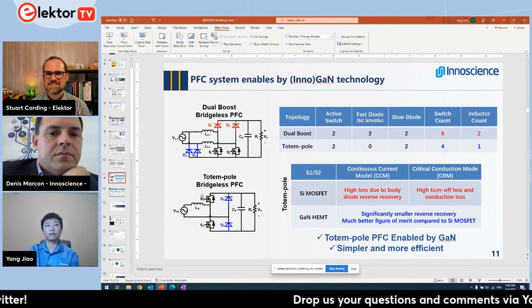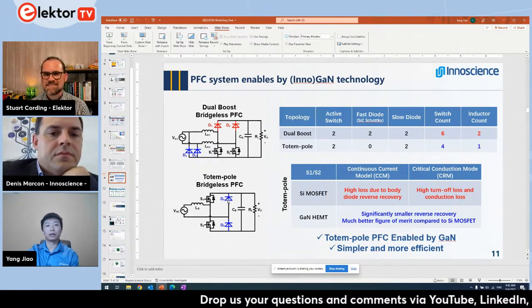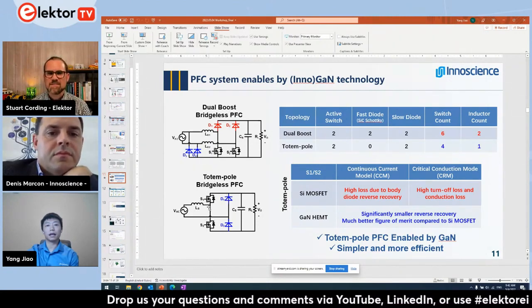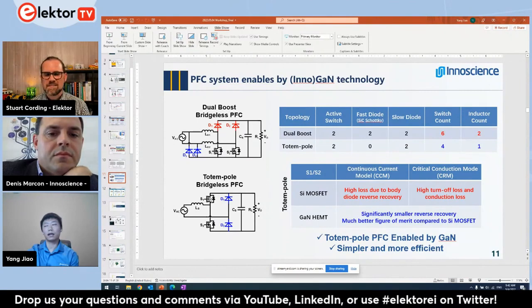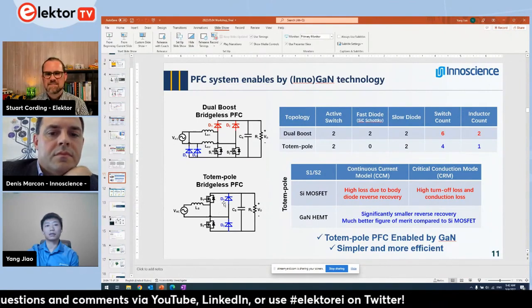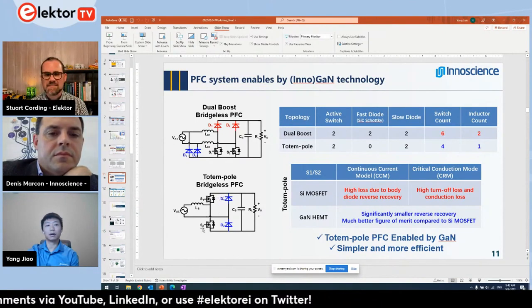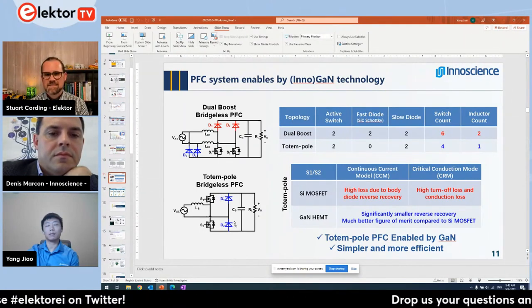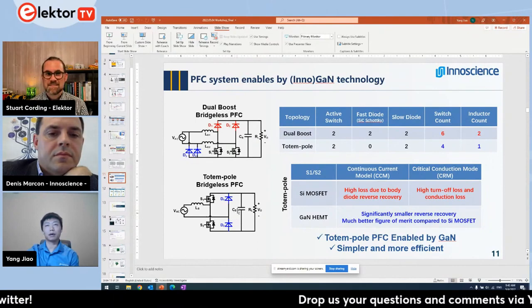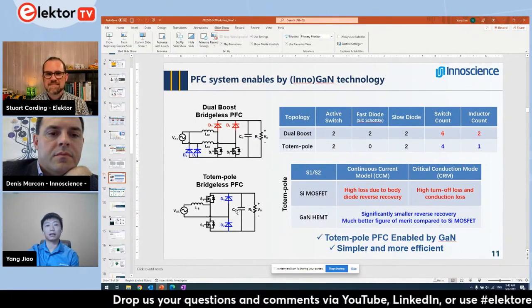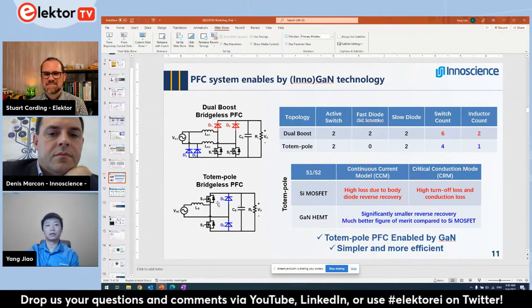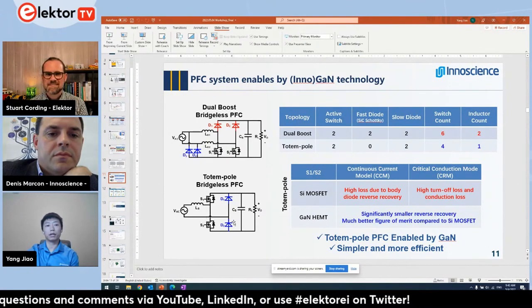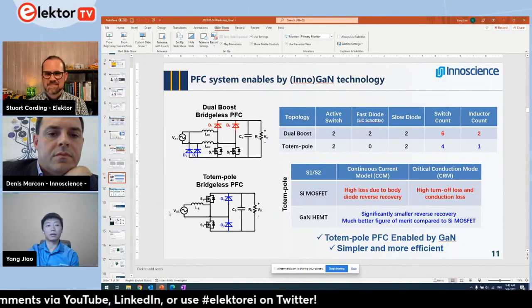Therefore, the totem pole PFC with a simpler structure can now be used. Right. But the gallium nitride device doesn't have a reverse recovery charge. As a result, this is a new topology recently enabled by the gallium nitride device in both the adapters above 65 watts and also some other higher power applications like server PSU. So this is an example of a new topology enabled by the gallium nitride device.